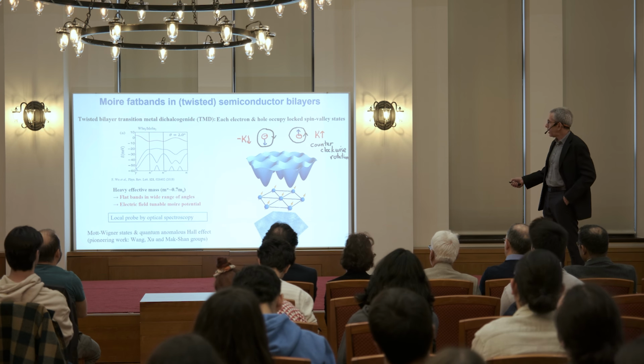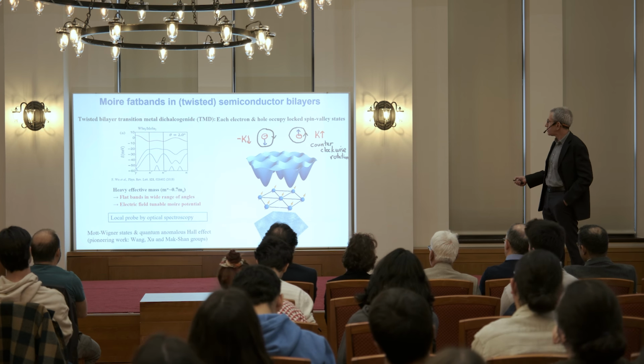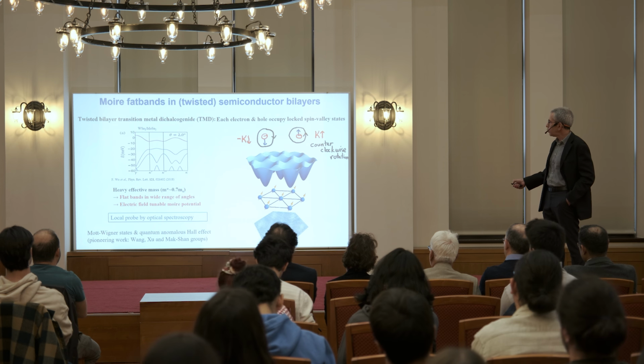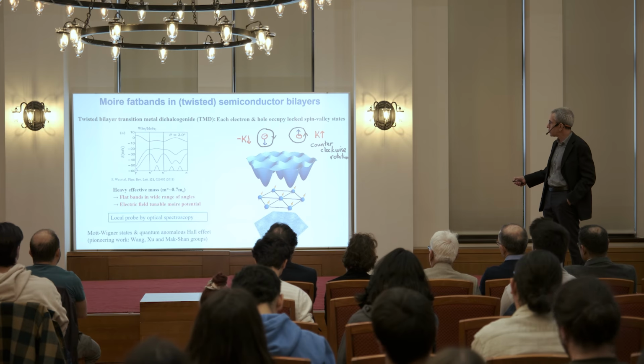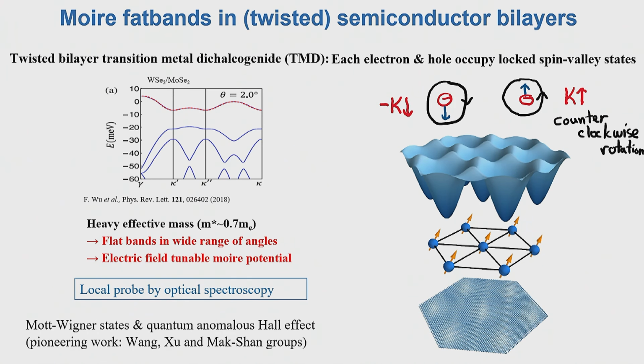And the same physics applies when you use semiconductor bilayers. In this case, this is a calculation for a particular structure, tungsten diselenide, molybdenum diselenide. And what you see here is, let's say, the top valence band, and the width of this band is telling you about how large the kinetic energy cost of this material system is, and that can be much smaller than the characteristic interaction energy.